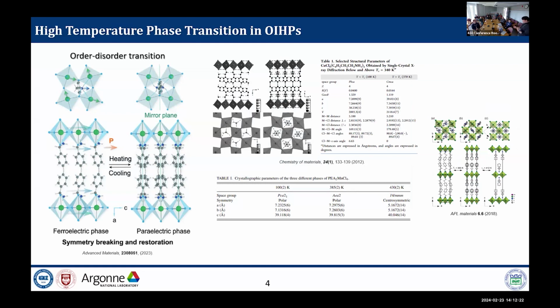So in PA2 copper tetrachloride, the room temperature phase is the disorder phase, and it has a polarity. When we go up to 340 Kelvin, the transition temperature, the state changes to the order state, and the system is centrosymmetric, so there is no polarity. Similar for the manganese system, the room temperature phase is the disorder state, so there is polarity, but over 385 Kelvin the structure changes to the order state, so there is no polarity. Because of this polar disorder state, there is some possibility to get ferroelectric property.